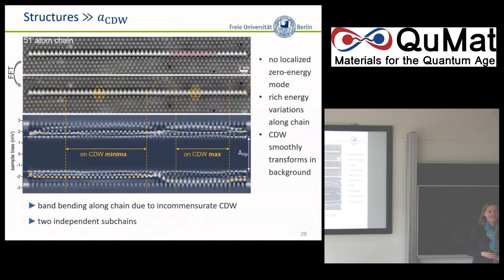Yeah. On a similar note, it almost looks like you get kind of domain formation. Yeah. Because of this, would that also impede Majorana searches then? Well, at some point we thought it could, because you have this band bending, and then anyway you have something happening there. But maybe I should also note, now here you have one of these chains that's rather long, and there had been theoretical calculations how fast these Majorana states should fall off, and there they figured out it's only on a few atomic sites. So from that theoretical prediction, it shouldn't.